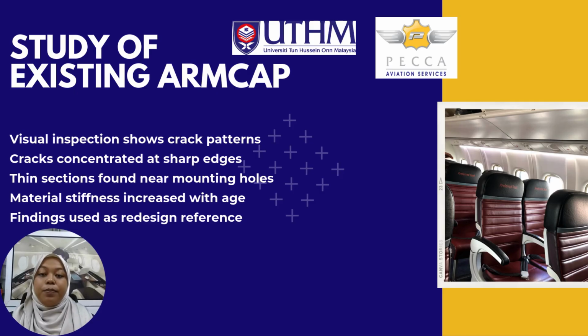So for this project, a study of the existing arm cap is a must. Visual inspection shows the crack pattern: cracks concentrated at sharp edges, a thin section found near the mounting hole, and material stiffness increased with age. The findings are used as redesign reference.